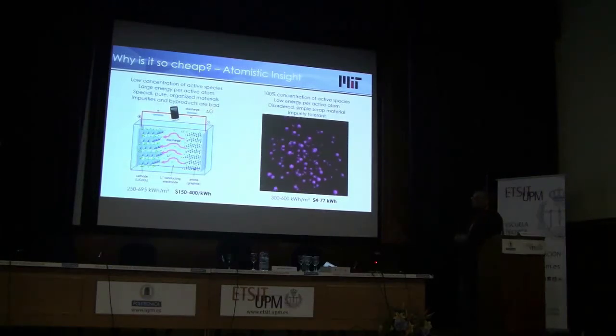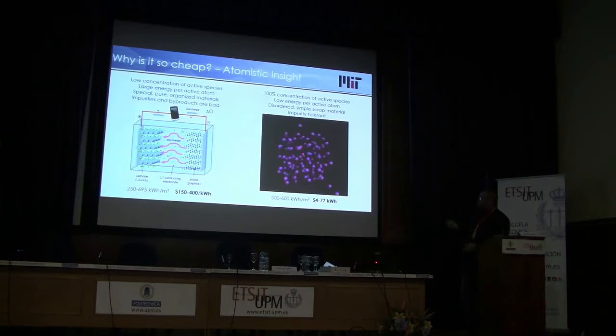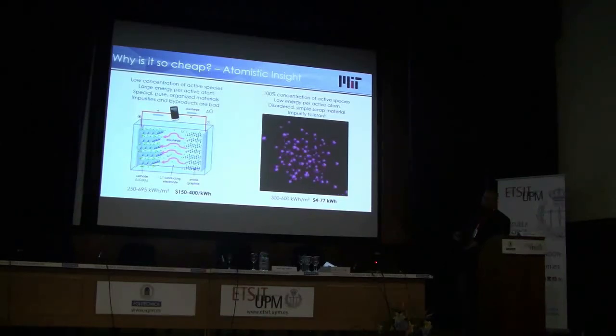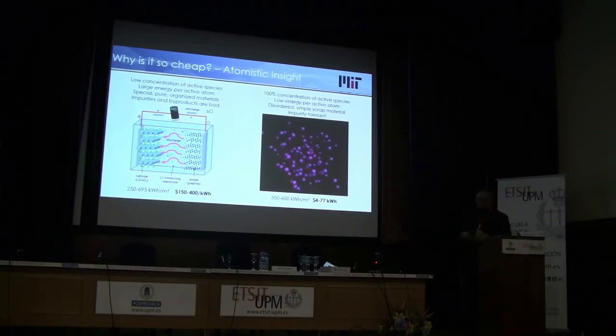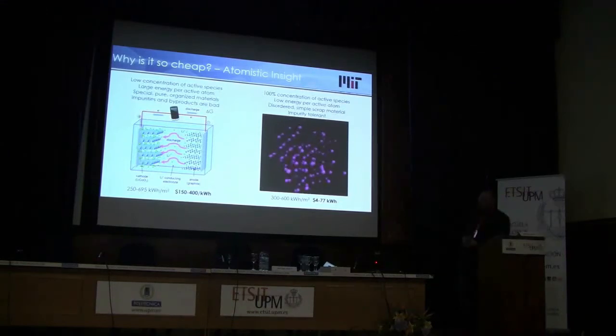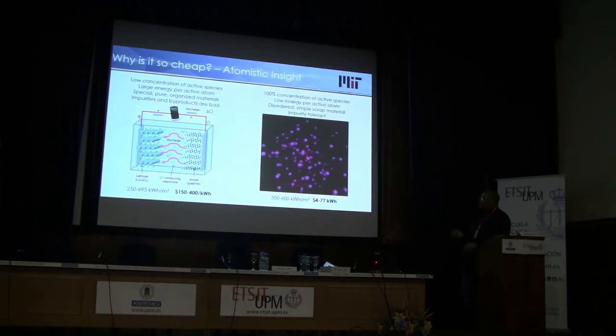And this is actually one of the reasons we're specifically focused on sensible heat rather than phase change. When you do phase change, you're breaking and reforming bonds. The way you break and reform them each time requires some care to make sure that you reproduce the same thing in the same way and you don't build up any new layers or different microstructure, or all the problems that could show up with regards to cracking the crucible or the container. And so just by heating and cooling, we are in a regime where things are quite simple for us and can have very long lifetime.